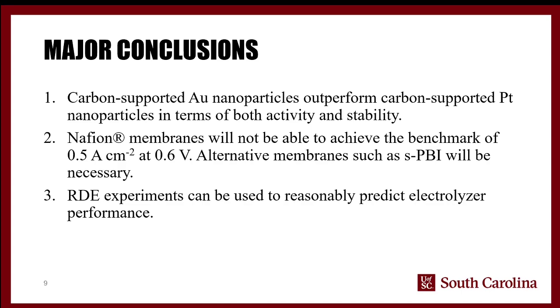As an example, we considered silver because there are some theory predictions that say that silver should perform as well as gold and platinum do in terms of catalytic activity. But what we find is that after the very first cyclic voltammogram with silver, the silver is completely dissolved or just reacts with the sulfate in solution. And so what you end up with is a catalyst that very quickly disappears.